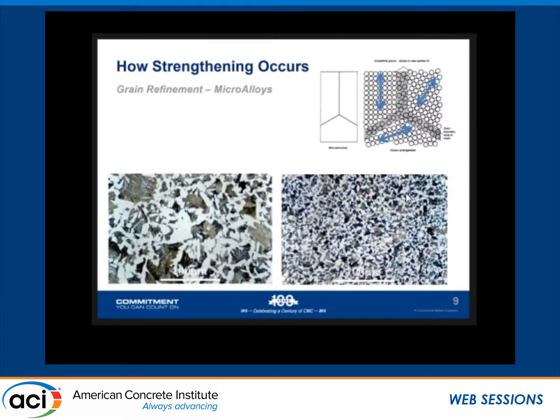Then you have grain refiners. Now what grain refiners do, steel grows in grains. Every one of these little circles where you can see a boundary around them, those are called grains. Now what happens in a grain, if you look, there's one grain, there's a grain, but the atoms are arranged in a different direction. Here they're arranged in a third different direction. It's geometry. So you get reinforcement, you get improved strength through geometry. Then you have this region of misfit where everything's out of line. That also contributes to strength.